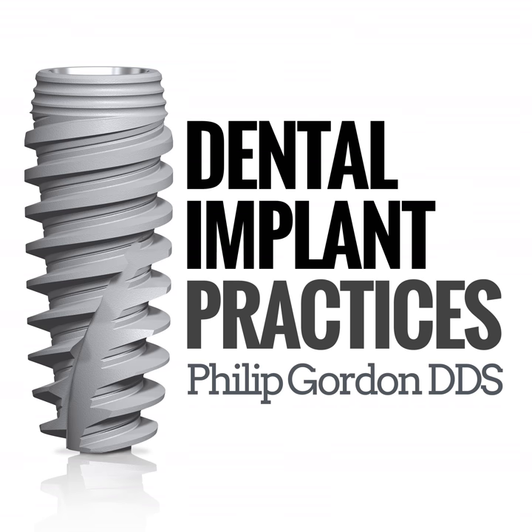We had gone away from the machined collar and started texturing everything all the way to the top. Jack dabbled back to that — he said he had the best success he ever had with implants that had four millimeter machined collars. I said, Jack, four is a bit much — can we do like one? And so that's how the Hahn implant ended up with the machined collar. It's a more hygienic surface in the environment where it's exposed to maybe transitory contact, brushing, where you're in that transition zone of the oral cavity. It's not as likely for plaque to adhere to a machined collar as something rougher. And that's kind of where the problem starts or doesn't start.